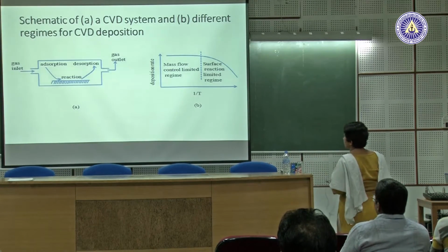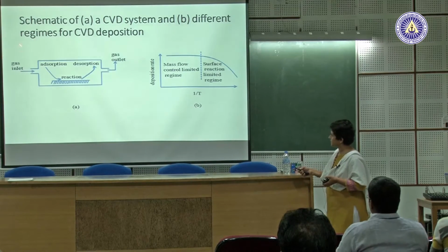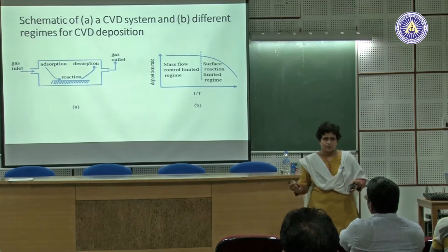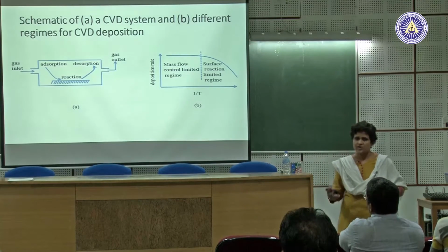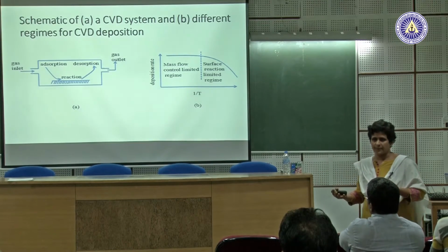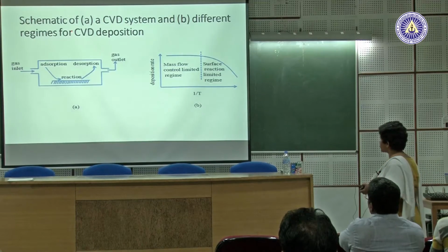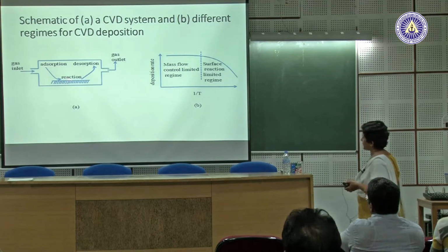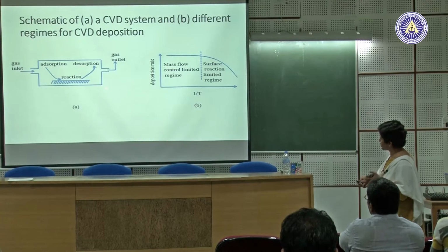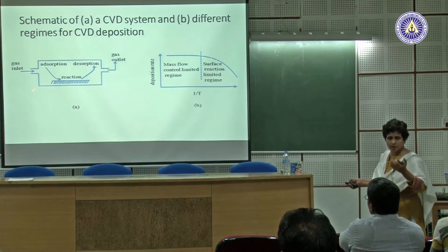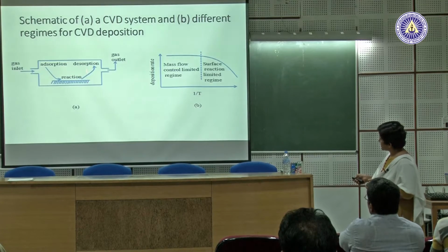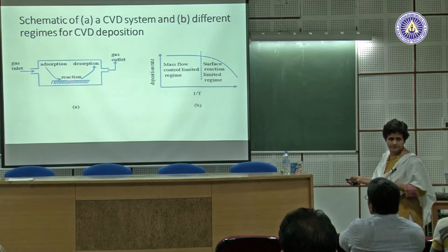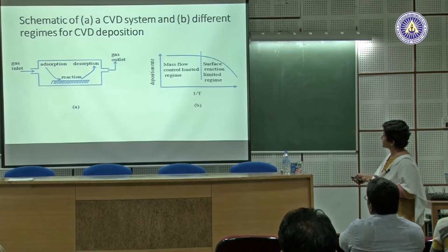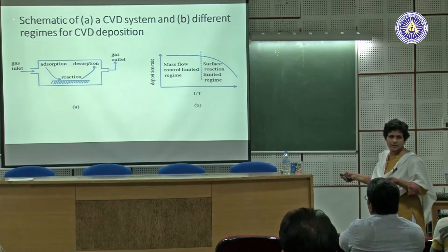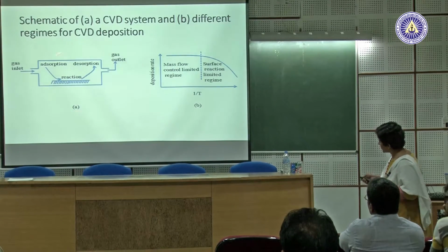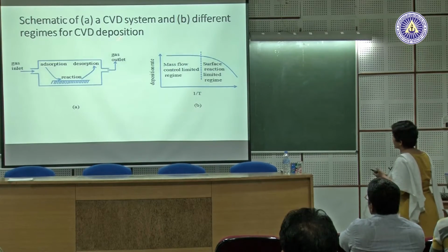In the case of chemical vapor deposition, normally the inlet source is a gas. So, you bring in the gas and then you control its reactions on a substrate by controlling the temperature and the rate at which the gas is coming. The gas is going to come depending on the surface property that you have chosen. It will get adsorbed, first as physisorbed and then chemisorbed. It may dissolve also, and it will also form a film here, and whatever product gases are left, they will come out. Okay. And then there can be a lot of good science in here, thermodynamics, kinetics.